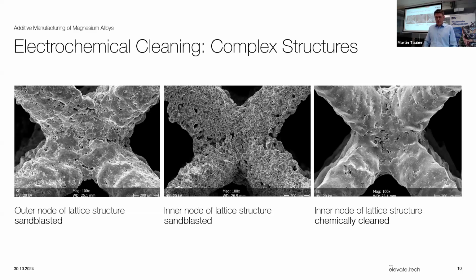First of all, you can see the outer node of such a structure can be cleaned quite well with sandblasting, but if you go on the inside, then it's already difficult because the sandblast particles don't reach that area. And with the electrochemical process, we can reach all regions and we can take away material from all parts that we want to. And of course, we have the advantage that we don't have any material being implemented into the material because we don't have any particles which might go into the surface area, and we only take away material.